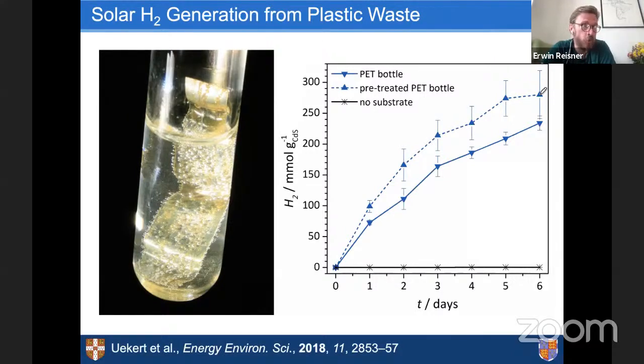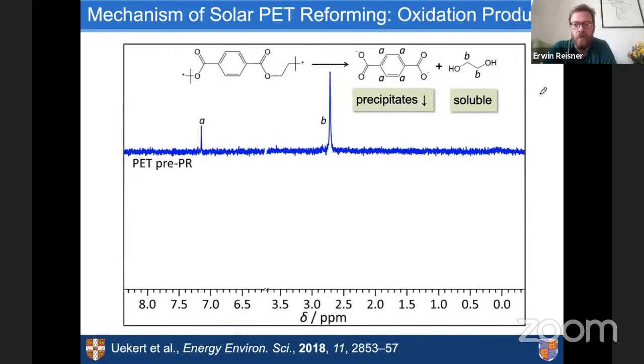Conversion yields, usually if we go to relatively but still fair substrate concentrations, we look at 30% conversion yields. So that's quite respectable. So it's not just a percent or a fraction that we break down. It is really a meaningful amount of the polymers. So how does the chemistry work? And this shows you how simple the chemistry, in fact, is again.